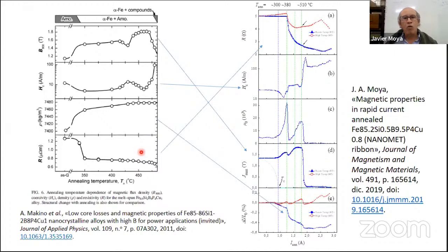Here we present our result obtained with a similar composition, not the same composition, but a similar type of composition, nanomet. And the results are very comparable to those made by Makino with the traditional method. In our case, here we have 80 experimental points. We have the measure at high temperature. Here is the critical temperature.